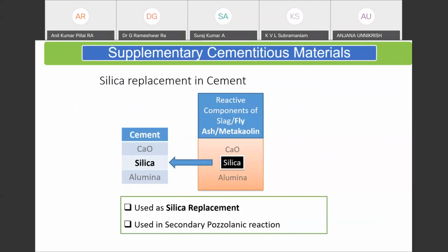And if you look at any of these waste materials like slag or fly ash and metakaolin, they basically contain calcium oxide, silica, and alumina. And I'm basically looking to replace the silica in the cement with the silica that comes from these waste materials. So basically, as a silica replacement now, this has become very standard. Replacement of cement with these waste materials is now a very standard way of reducing clinker factor in cements.